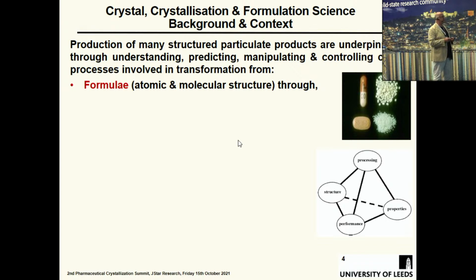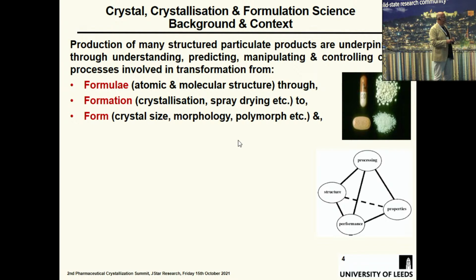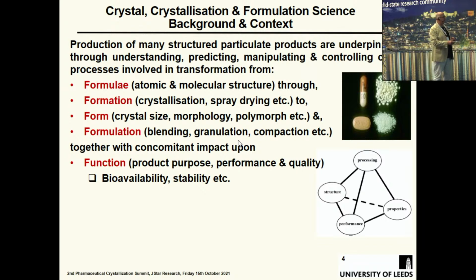We start with a formula, which is a molecular structure. From there, we go to the formation: crystallization, spray drying. That produces the form, which is the crystal size, the morphology, the polymorph. And from that, the formulation, which we might do by blending, granulation, compaction, and that impacts on the functions. And that, through Calvin's concept of the material structure tetrahedron, tells you the kind of things you want to do, how these various factors relate.